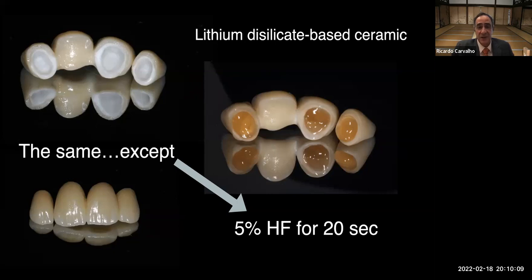We etch with hydrofluoric acid, with only one difference here. The acid concentration is lower, and we etch for only 20 seconds. The silanization process afterwards remains the same. I apply silane, I wait for the solvent to evaporate, a thin layer of silane, and all these other aspects. The only difference is in the etching step.